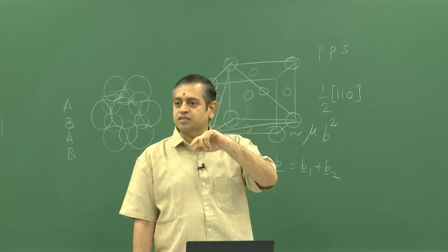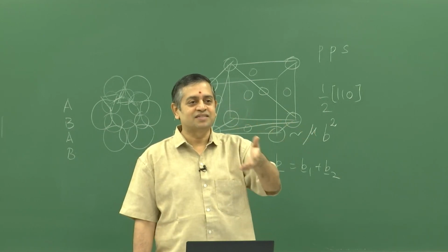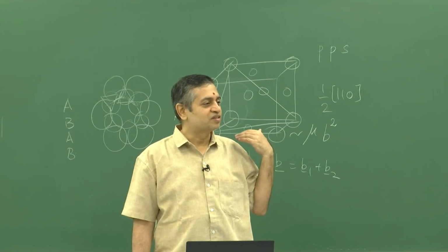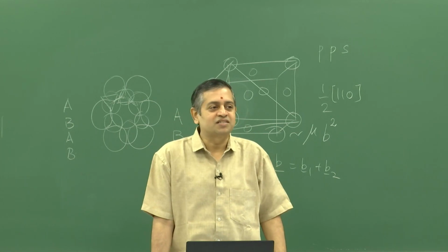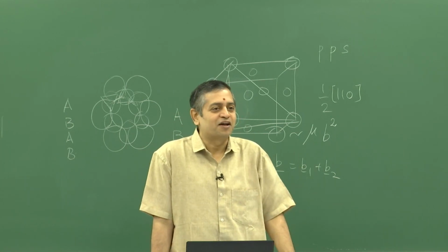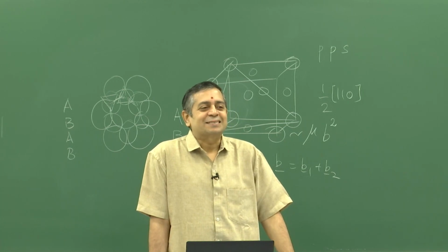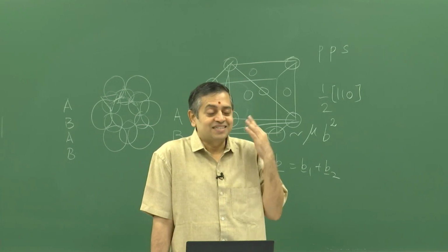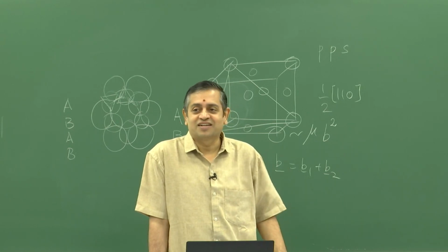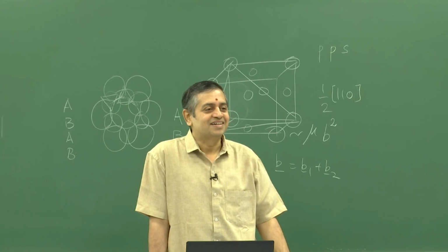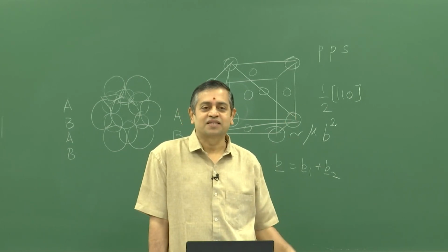This is not the case with experiments, or at least we assume that in experiments all possible realizations have happened. And I do not know if, with some aluminum, the spacing of partials also would show differences depending on how many aluminums are there. And in this case it is worse because aluminum prefers to go sit in the stacking fault, which is known as the Suzuki effect, which is something we will learn next week. I will also show you scripts, and that is from Sushi's thesis work.